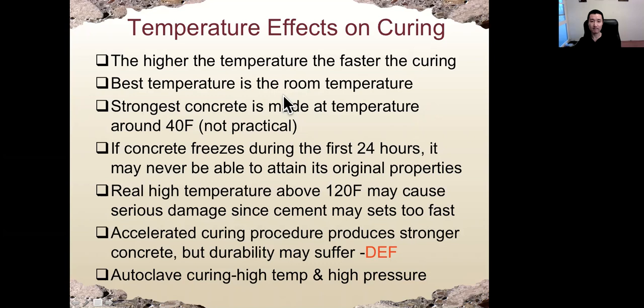The stronger concrete is made at temperature around 40 degree Fahrenheit. The freezing temperature is 32, so it's just above the freezing temperature. But it is not very practical to cure the concrete around 40 degree Fahrenheit. But the stronger concrete is made at around that temperature, just above the freezing temperature. That is because hydration will keep going on since the temperature is not too low, above freezing, but it is very slow, so we have very homogeneous hydration product.